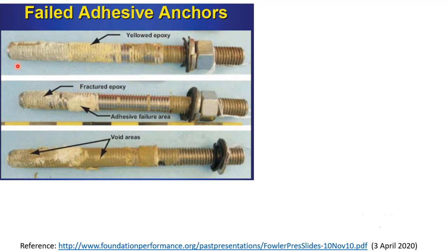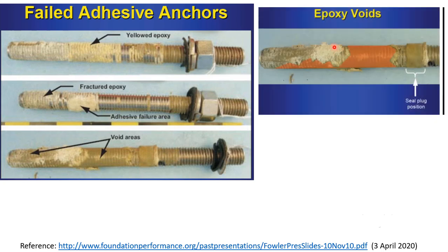So these are the anchors which actually failed, and you can see the yellowed epoxy. Yellowed epoxy basically means it is a degraded form of epoxy. Because of improper curing, it can turn yellow. Then you can see fractured epoxy near the tip of the bolt. This fracture happened because of the brittle behavior of this epoxy. And also you can see void areas, where there were a lot of voids in this epoxy. Voids will lead to weakening of the joint. Similar voids can be seen here as well. So these were the issues that were found after investigation.